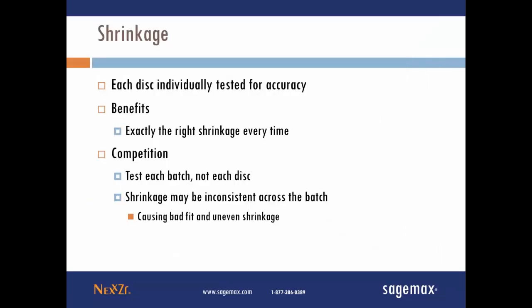The shrinkage of our material is something that is extremely important to us, as we feel it's very important to all of the technicians out there. Sagemax actually goes through the effort of testing every single zirconia disc that we make. We do that to ensure the accuracy, that every zirconia unit we make has the exact right shrinkage for that unit. What we see from our competition is they tend to test just one batch. So you might get several hundred units that all have the same shrinkage. But what that means for the consumer is it's not entirely accurate. Each piece should be measured because each piece is going to be just a little bit different.